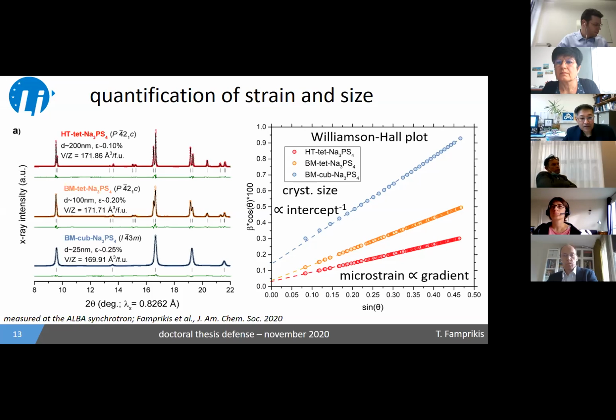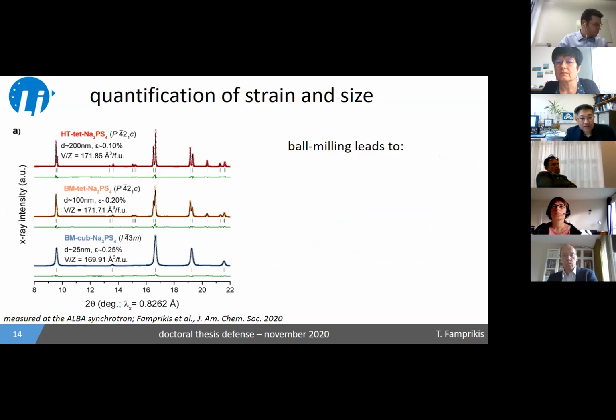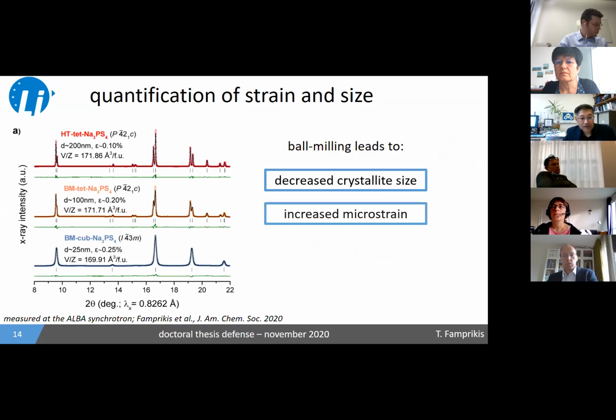The average deviation between the size, the lattice volume of crystallites, of different crystallites in the material. So again, we see an increased microstrain for the ball mill material as compared to the tetragonal sample. So to summarize, ball milling in Na3PS4 leads to decreased crystallite size, increased microstrain, and a compressive macrostrain, so a decreased lattice volume. So all these effects can be thought of as coming from the mechanical nature of mechanochemistry, that is, the synthesis of materials through the application of constant mechanical force and pressure.